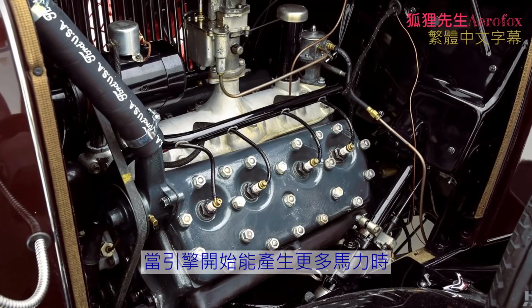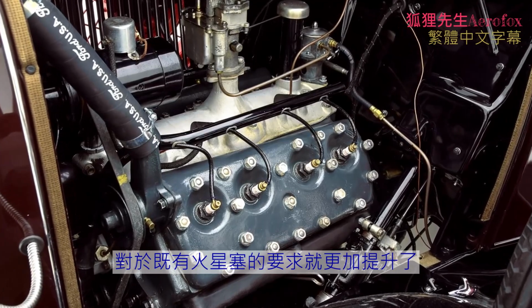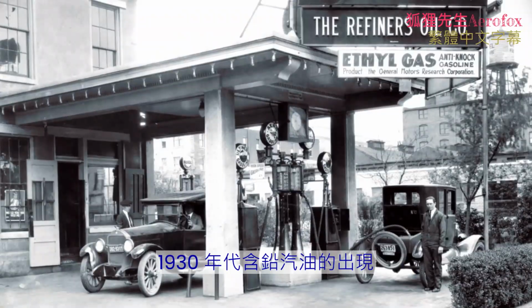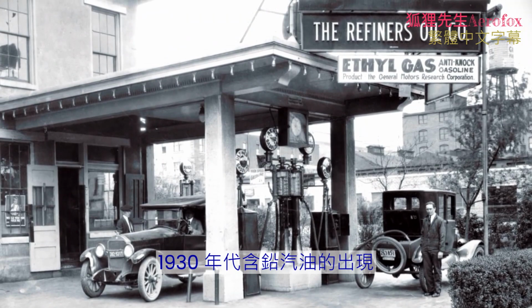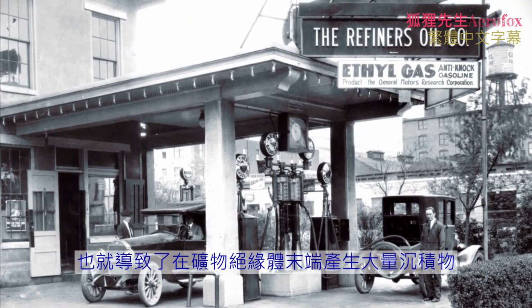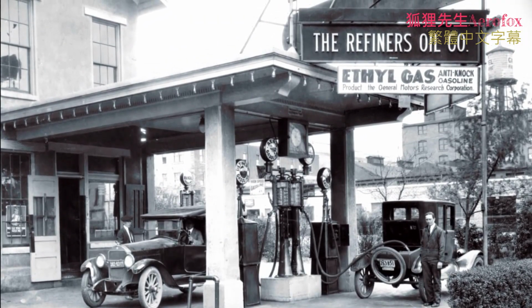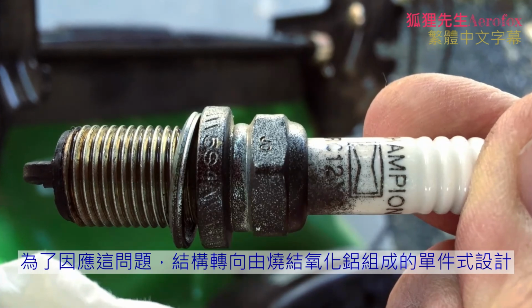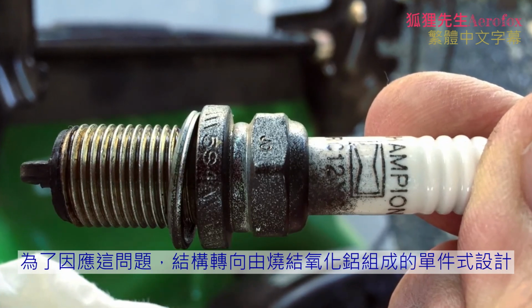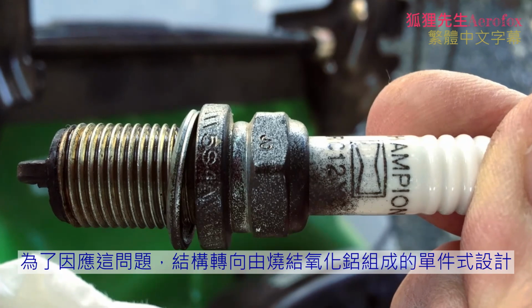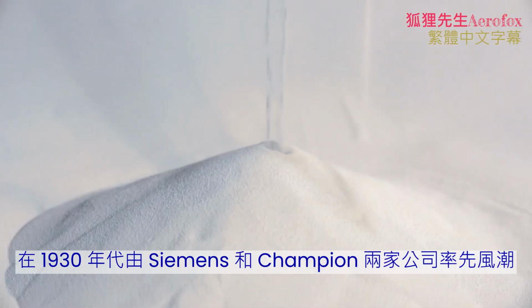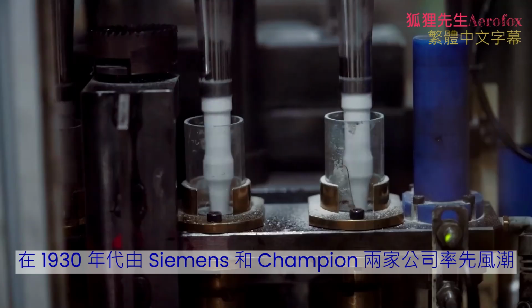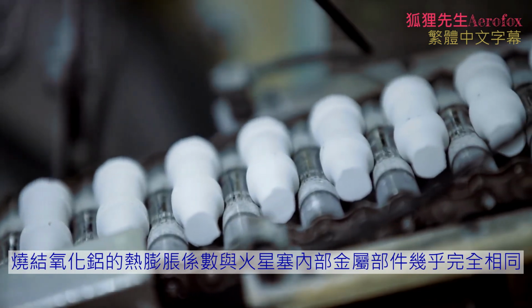As engines began to produce more power, the demands on existing spark plugs started to increase. The emergence of leaded gasoline in the 1930s would also cause aggressive deposit buildup on the mineral insulator ends. To keep up with this, construction was shifted towards a single-piece design composed of a ceramic called sintered alumina. Pioneered by both Siemens and the Champion Ignition Company in the 1930s, sintered alumina had almost the same thermal expansion